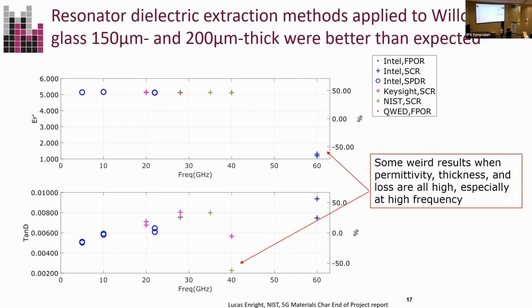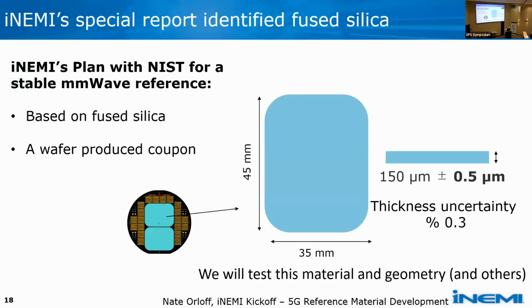As part of that first project, just for fun, the graduate student who's working with Nate Orloff also measured some of the Willow glass. Because of the higher dielectric constant, and it was 150 and 200 micron thick glass, which I guess is thick for them, there were some odd measurements up at the highest frequencies. But it's kind of nice to see that there's going to be some nice data on all kinds of materials as this project moves on.